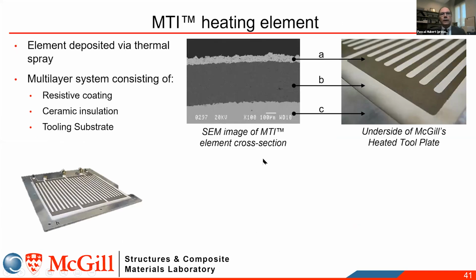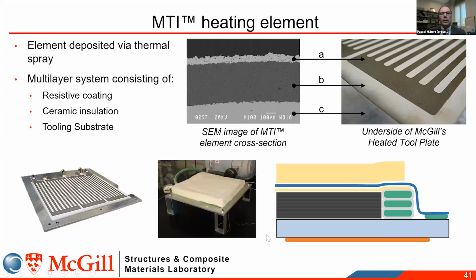We've actually used a technology that was developed in Montreal, the MTI heating element. The way that it worked is that the heating element was sprayed directly on the tool surface through thermal spray. So what you see on the image here, C is your tooling substrate, B is your layer of ceramic insulation, and A is your resistive coating or the heating element. And here you see a simple tool that was manufactured, like a small plate. And what you see is the underside of the tool.